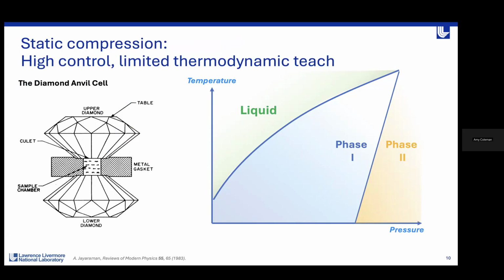The first one that I'm showing here is static compression techniques. So this can be using things like diamond anvil cells. And this is a very well-established and strong and stable technique for generating these extreme pressure states. And the way it works, to simplify it, you have two diamonds. You have a chamber in the middle where your sample goes, a metal gasket around the outside, usually some sort of pressure transmitting medium in the chamber, and you can squash these diamonds closer together and really increase the pressure in your sample.